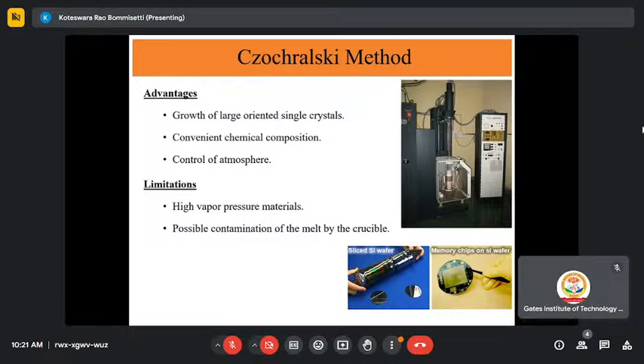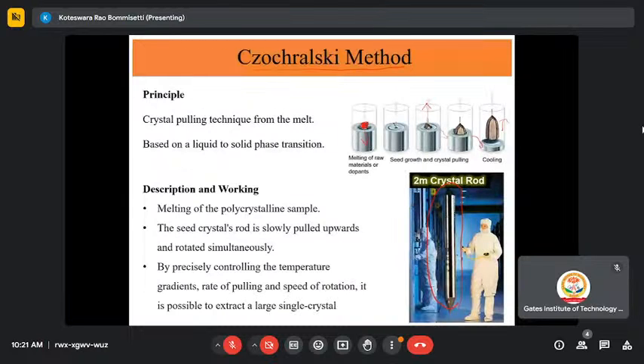And there is always a possible contamination from the crucible. Because when you are using such large size crystals, you have to melt them in some crucible. This is the crucible. This crucible is also nothing but some chemical element, aluminum oxide or platinum or whatever. Preferably they use an oxide type of crucible for melting the metallic type of elements. So there is always a possibility of contamination of the crystal with the container. That we cannot avoid. That is the one drawback in this technique.